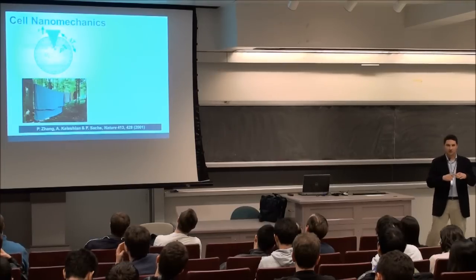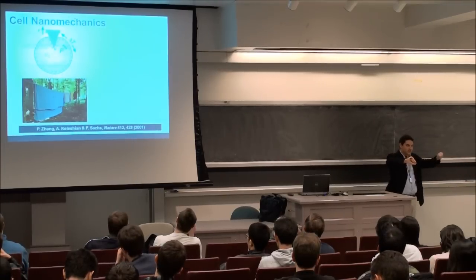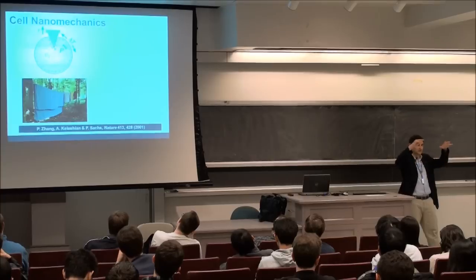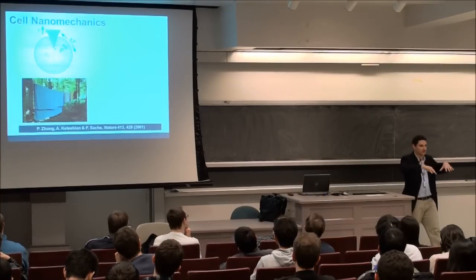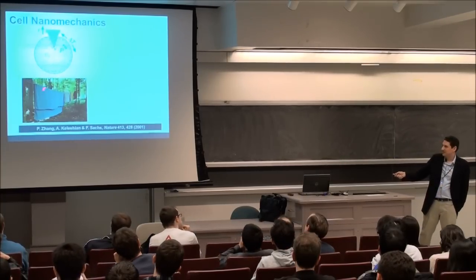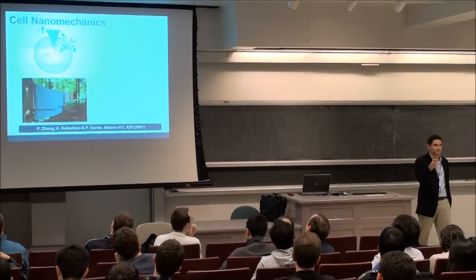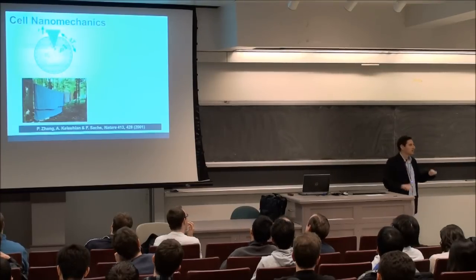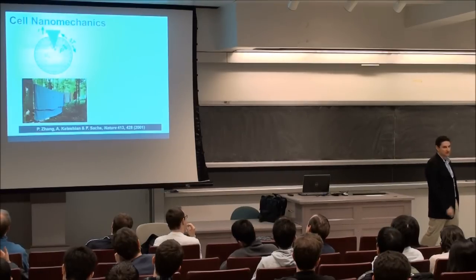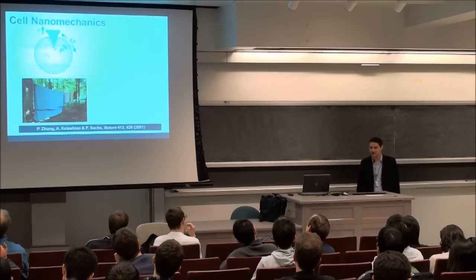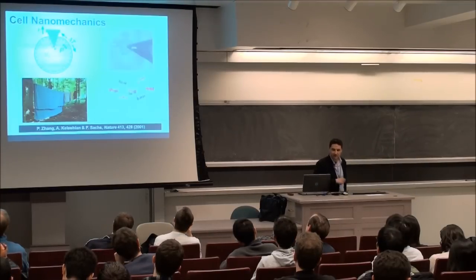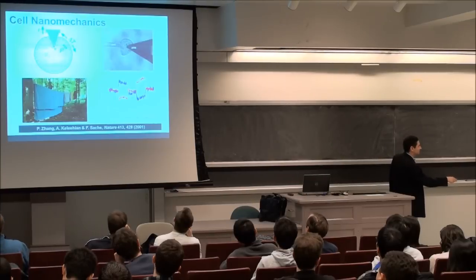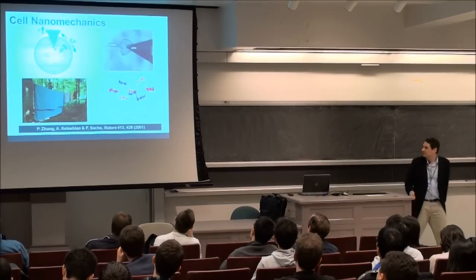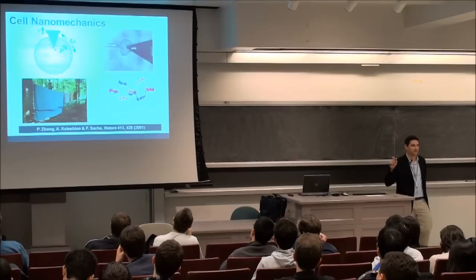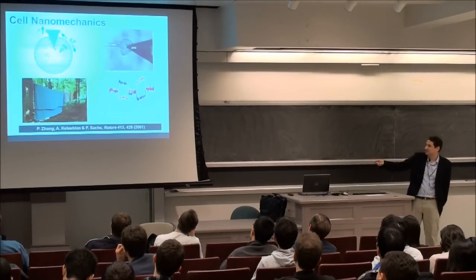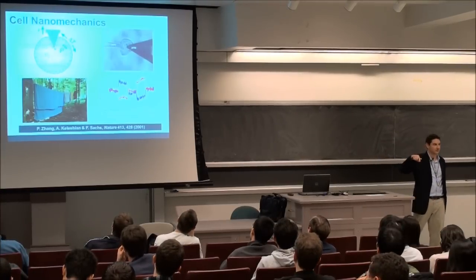It's just like when you have clothes on a clothesline. If you change the tension on the clothesline, the whole thing is going to go up, so the clothes are going to go up. So if you had an AFM probe at the top of your clothesline, it would go up based on changing that tension. The tension is changed by polarizing the cell. That's the flexoelectric effect, and you can see it here. Here's the response. You can see that most cells change on the order of a nanometer, a very small amount, due to this flexoelectric effect as you polarize the cell. So they're using a patch clamp here to polarize it and the AFM to measure that displacement.